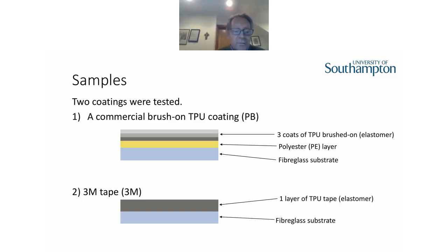The systems that we looked at here: the 3M is the standard tape, so we used that as a baseline, if you like. That was one layer of the polyurethane 3M tape on the glass fiber substrate, which is a typical makeup of a blade. And then we were looking at a commercially brushed system that was slightly more complicated.